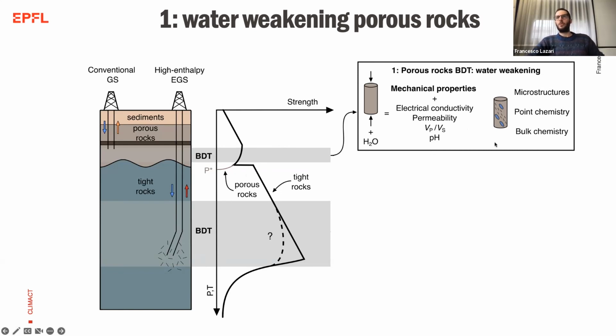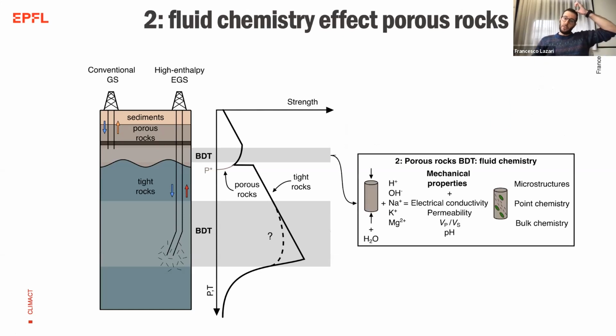Once we have the deformed samples, we're going to look at the microstructures under the microscope, and we're going to do also some point chemical analysis and some bulk chemistry to see whether we had any chemical reaction in the rock also after the experiments. After that, we're going to do basically the same, this time adding, instead of pure water, chemically more complicated water, which means low and high pH, and we're going to enrich the water in specific ions such as sodium, potassium, and magnesium. Then the rest of the protocol will be just the same.